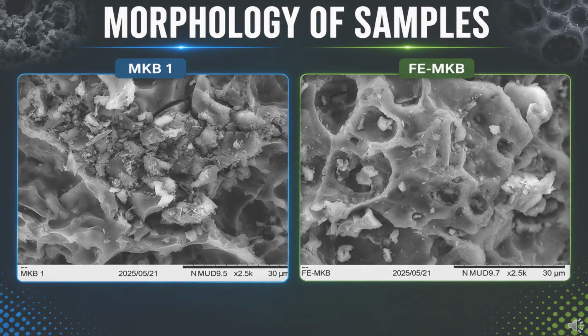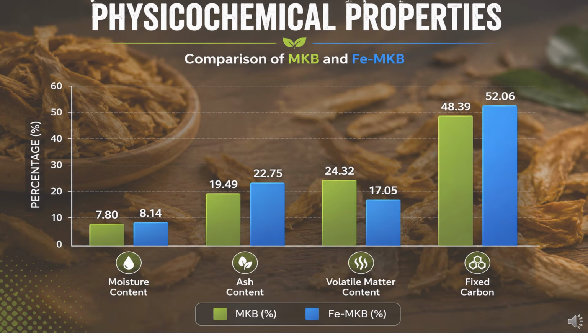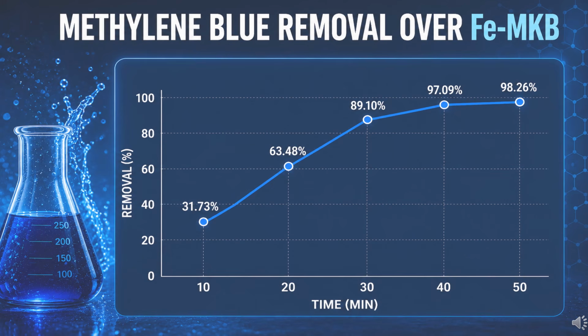The SEM image of MKB showed a rough and uneven structure with partially formed pores, while iron-decorated MKB showed a porous network with multiple pore openings, indicating that iron impregnation had successfully activated the network. Proximate analysis estimates four major variables, which are moisture content, ash content, volatile matter, and fixed carbon. And an increase in fixed carbon and ash content in iron MKB showed the effectiveness of this material as an adsorbent. Iron MKB showed effective adsorption of methylene blue with the highest removal of 98.26% achieved in only 50 minutes.